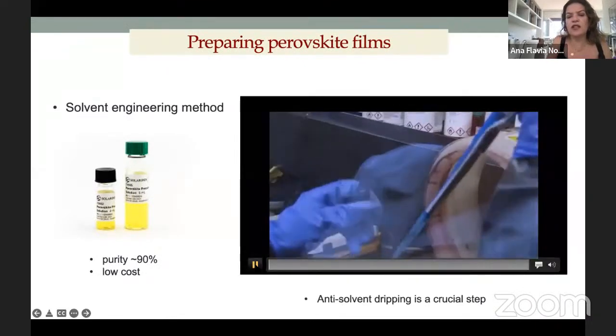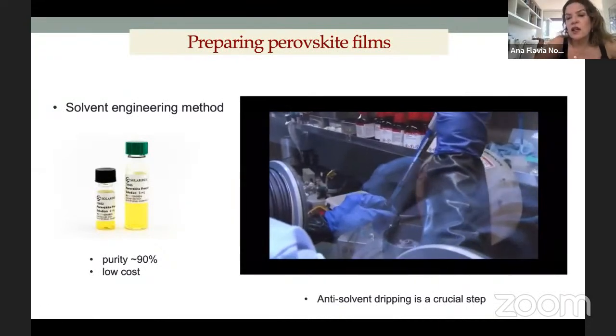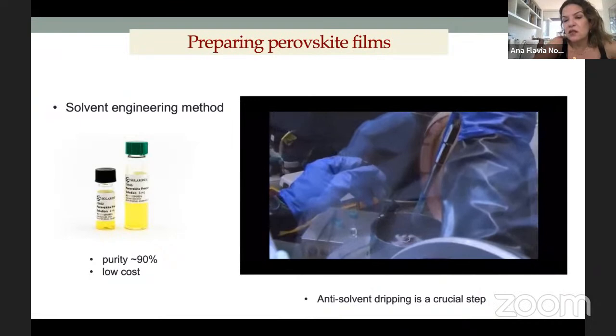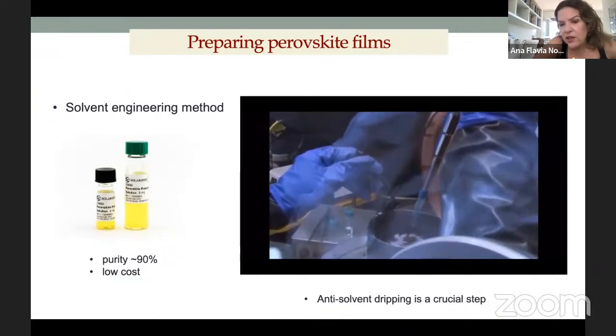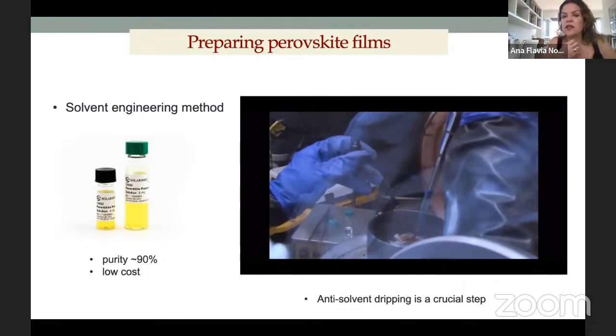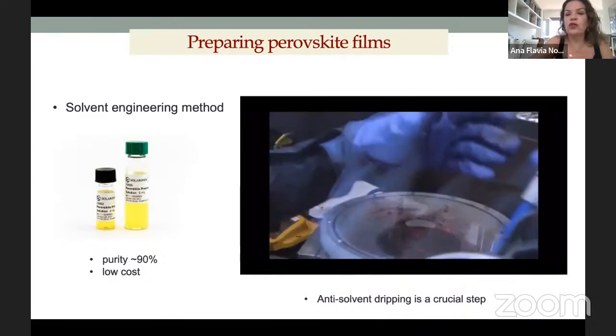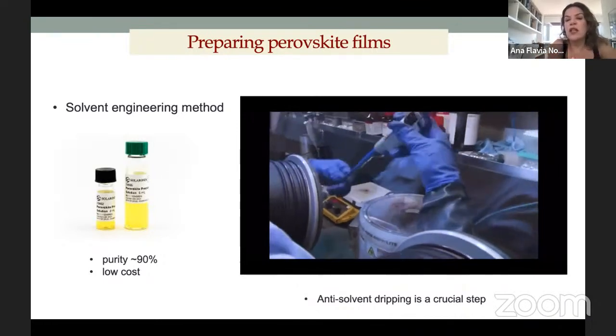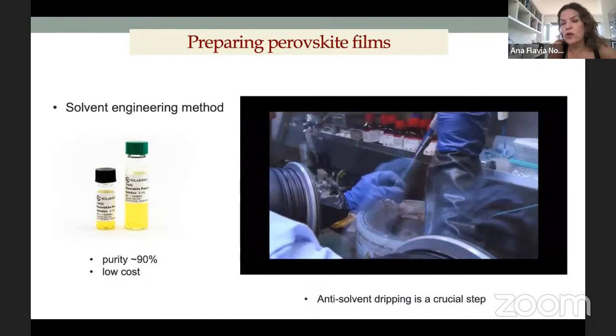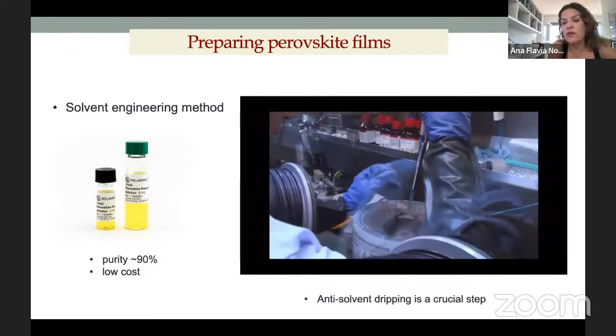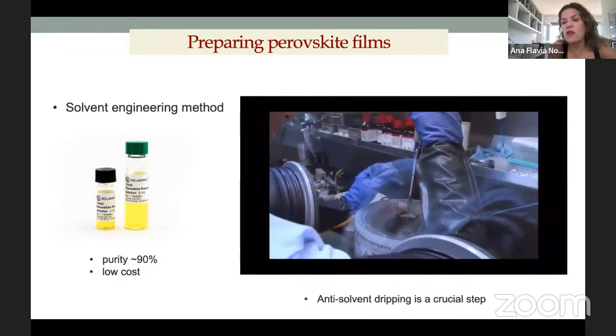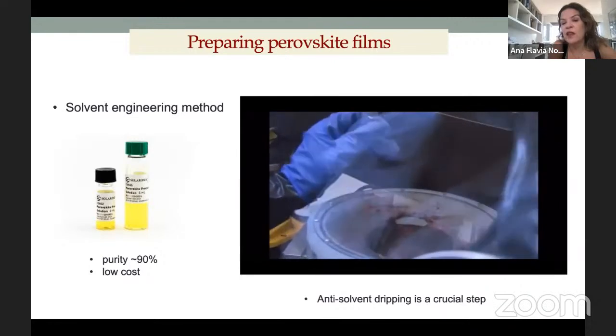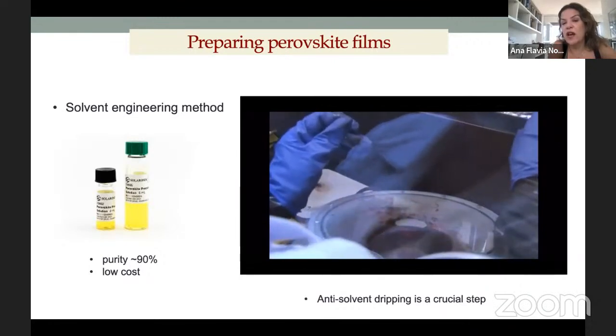So this is a video and this is my postdoc, Fran. Now she's going to deposit the layer, the solution. I want you to just pay attention to the change of color as soon as she drops the antisolvent. So in our case, we're doing this inside of a glove box, but we can also do it outside of the glove box. There's not a huge difference in terms of efficiency. Can you see now? There's a change in the color. And then you have the formation of the perovskite in this step.